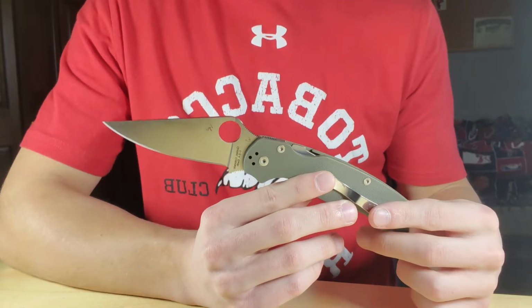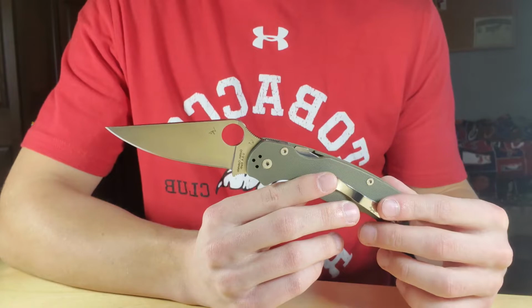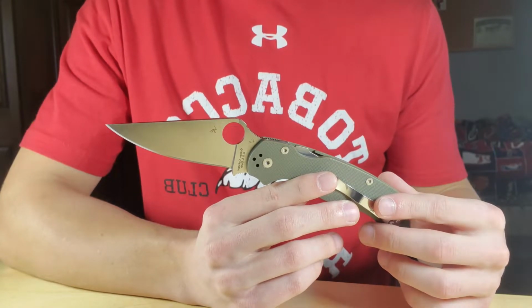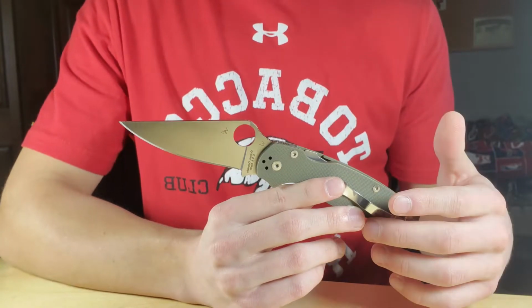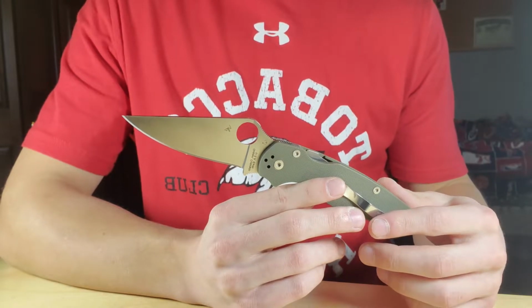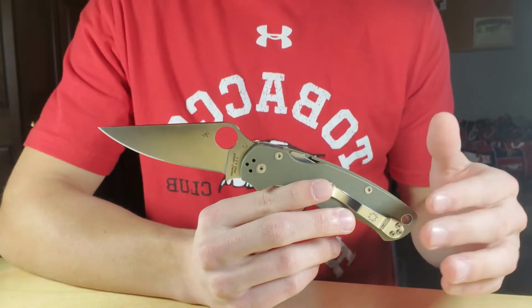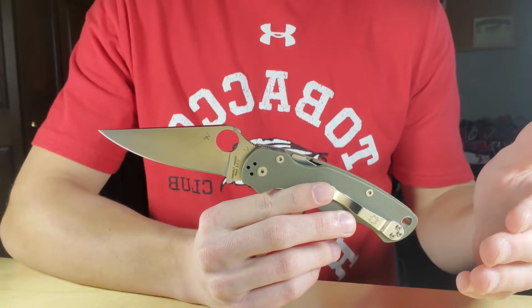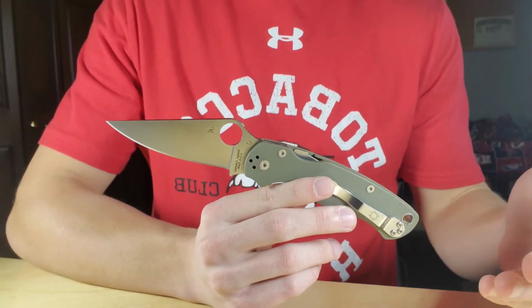If your stones aren't hard enough to abrade those carbides, you're just going to wear the matrix around them, which leads to a weaker edge since they aren't firmly secured any longer. Your edge is also going to be less refined since the carbides are left all jagged with all that material missing around them. You can kind of see what I'm talking about right here.